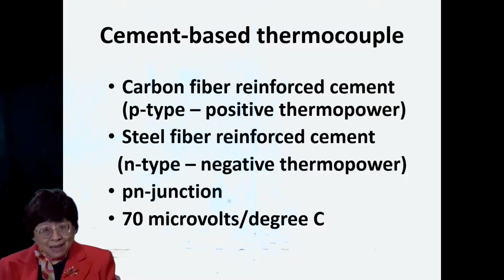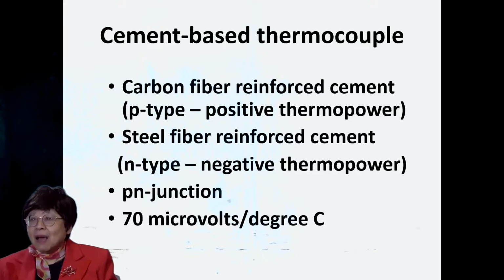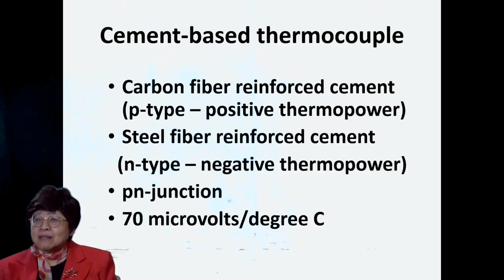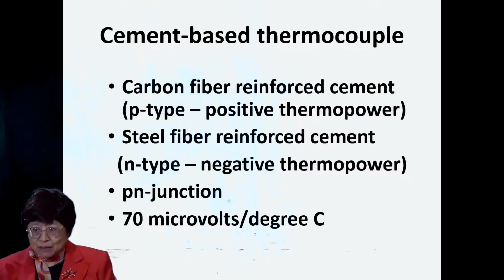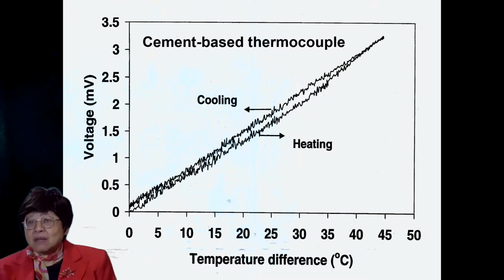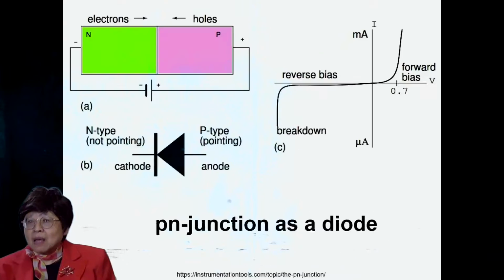Another method of temperature measurement involves the thermocouple, two dissimilar materials electrically connected. And we can have a cement-based thermocouple, with one material being carbon fiber cement, which is P-type, with positive thermal power, and the other is steel fiber cement, which is N-type with negative thermal power. So one forms a p-n junction, that is the two materials in intimate contact, and it does work. This is the Seebeck voltage versus the temperature difference.